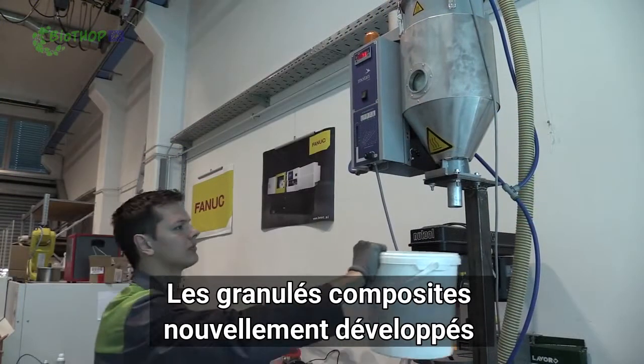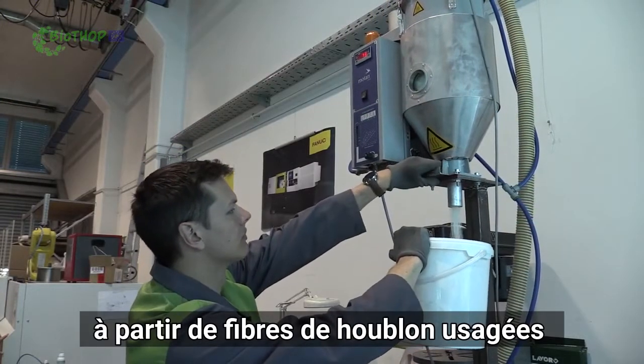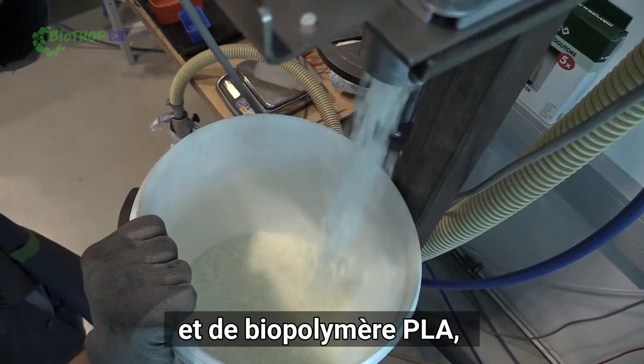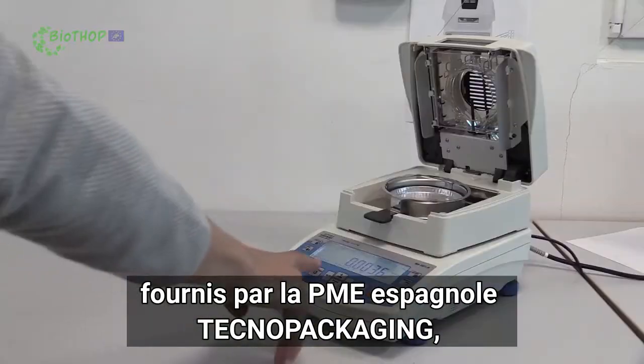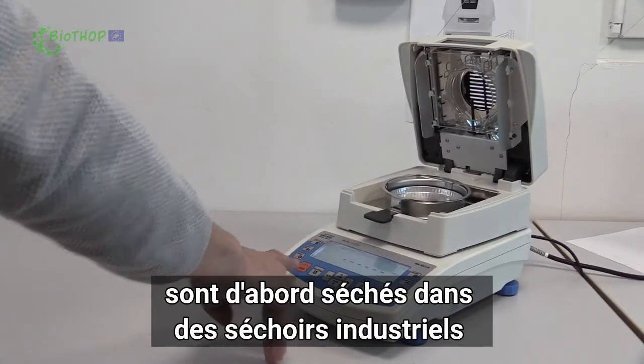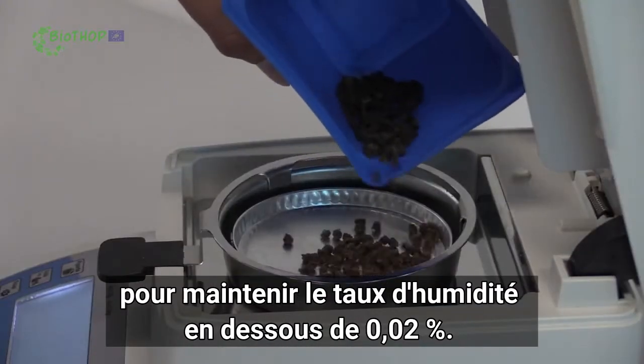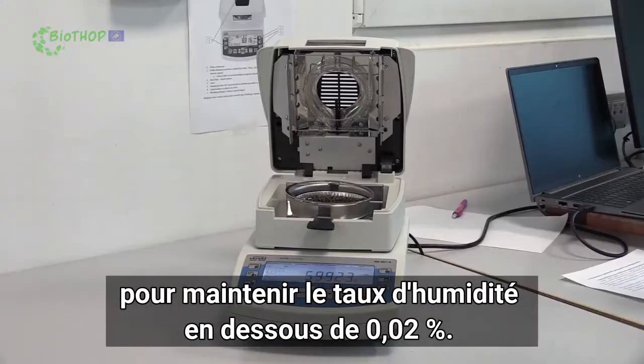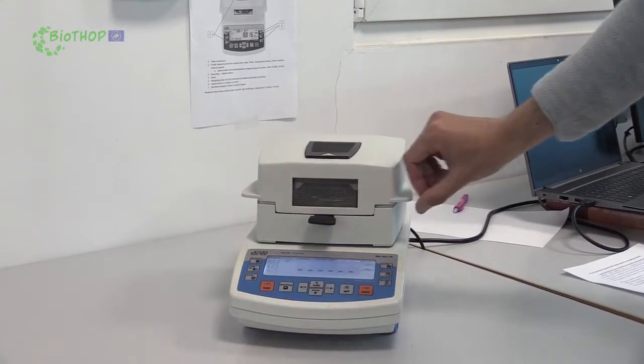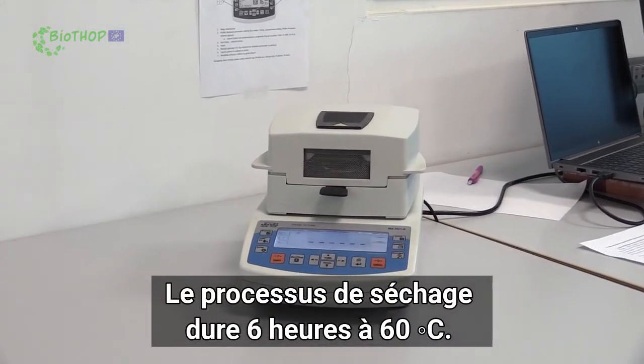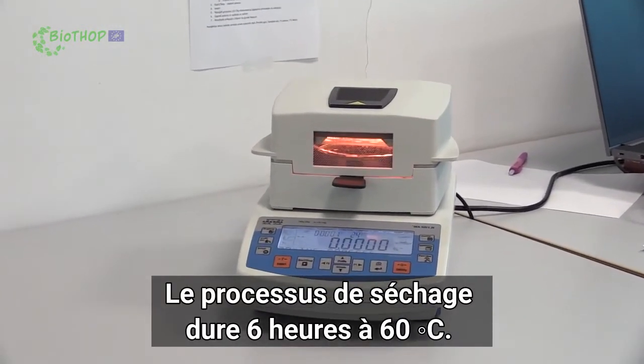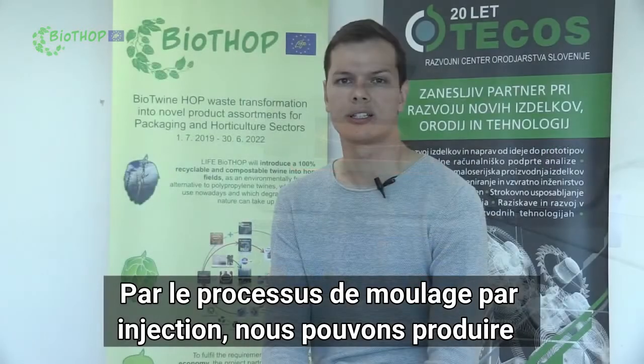Newly developed composite pellets from wasted hop fibers and PLA biopolymer received from Spanish SME Technopackaging are firstly dried in industrial dryers to keep the moisture level below the 0.02%. The drying process involves 6 hours at 60 degrees Celsius. By injection molding process, we can produce high amount of products in very short amount of time. So it's very rational and efficient process for a mass production.